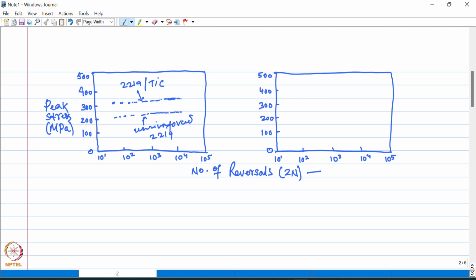Okay, so this is under artificially aged condition, which gives rise to a cyclically stable behavior. On the other hand, if you take the same material and do the fatigue testing in naturally aged condition, then in that case it is not cyclically stable. It might show cyclic hardening or softening, but even in that case the composite shows higher fatigue life or higher saturation stress compared to the unreinforced alloy. Okay.